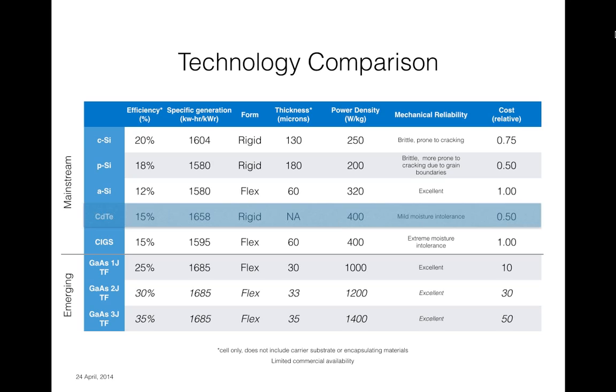And making them thin is important because by making them thin, you can dramatically reduce the cost. A space-based solar cell that's 30% efficient is going to cost you $250 a watt. And that's because it's built on a wafer that's 125 or 130 microns thick. And you have to bear the cost of all of that expensive gallium arsenide. But if you can make it very thin, of just a couple microns, and in fact the solar cells that I'm identifying here, that 30 micron thickness, only one micron is the actual solar cell.